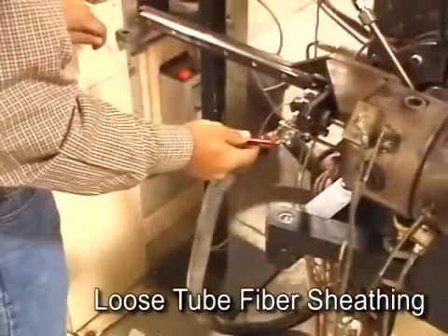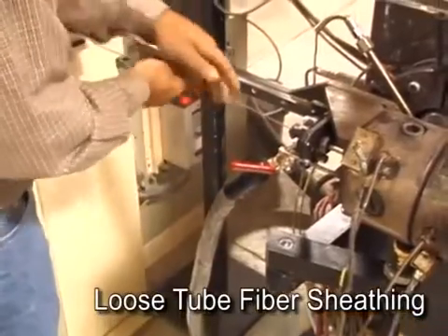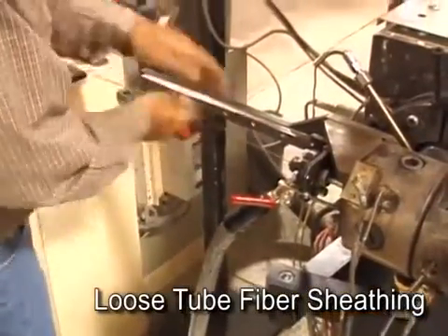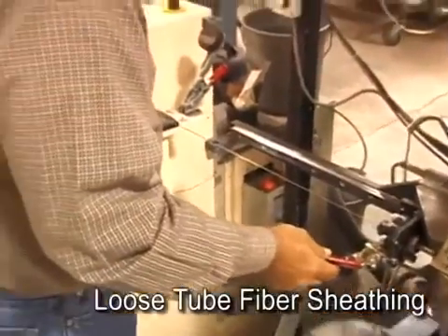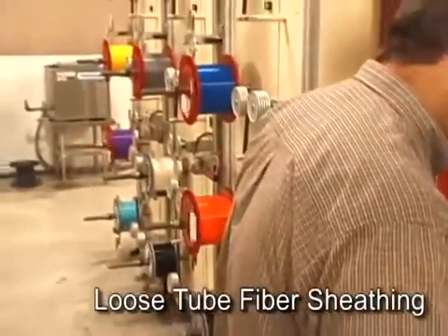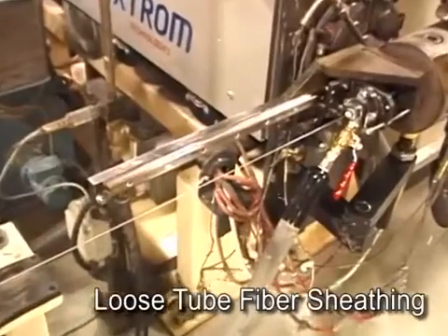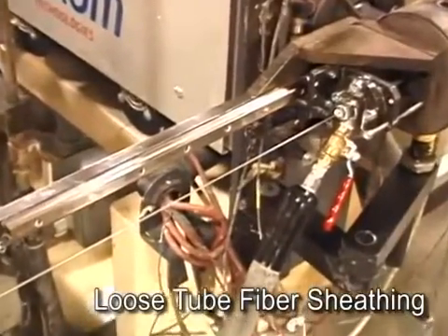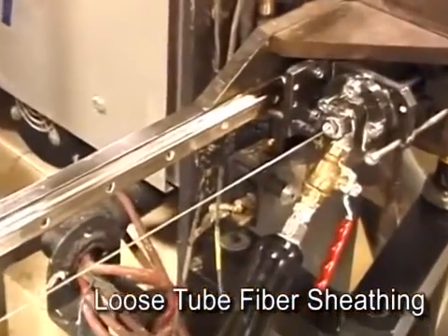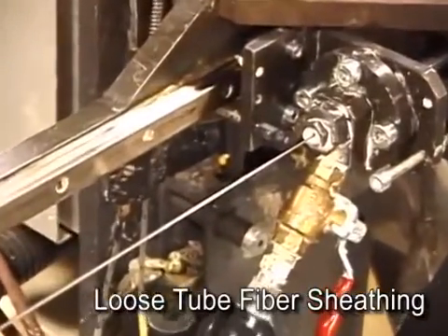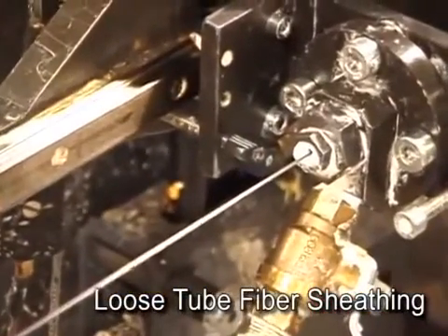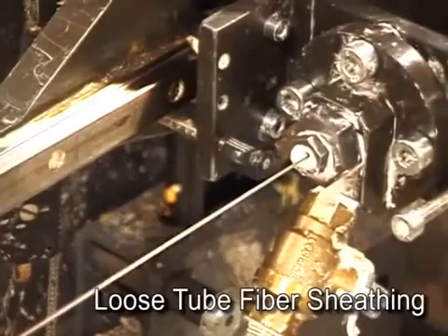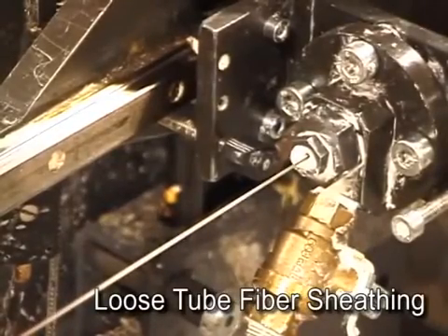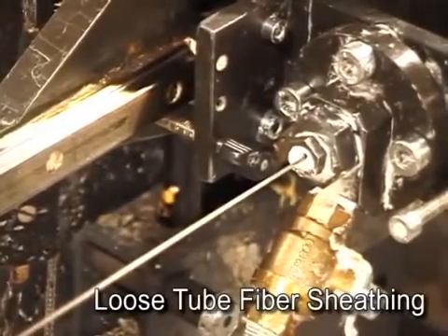Here we see a sheathing process for OSP fiber cable that begins with a number of reels of color-coded fiber loaded onto a machine that supplies each fiber at a constant rate under computer-controlled tension. The fibers come together and are fed into an extruder head that performs two main functions. First, a flow of moisture-blocking gel surrounds the fibers. Then, molten colored plastic is extruded around the fiber bundle to form a loose tube around the fibers.